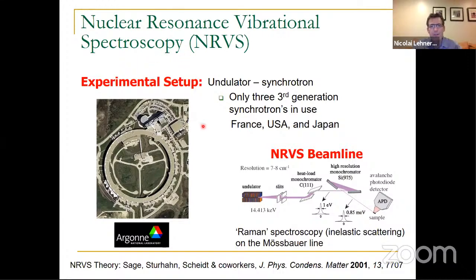And in nuclear resonance vibrational spectroscopy now, we're looking at the nuclear transition of iron 57. So we have to prepare our complex with iron 57, the 57 isotope of iron. And that, of course, is the Mössbauer active isotope, right? Mössbauer spectroscopy measures the nuclear transition between the nuclear ground state and nuclear excited state that is metastable of iron 57. And that's traditional Mössbauer spectroscopy. Here what we do is we actually measure inelastic scattering. So we measure the inelastic scattering that comes from exciting the complex at the Mössbauer line. And in order to do that, we need a very bright X-ray beam, and we need the exact light energy, which is 14.413 kiloelectron volts of energy.